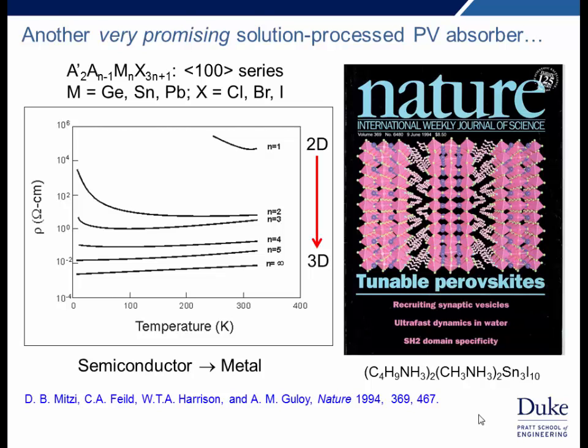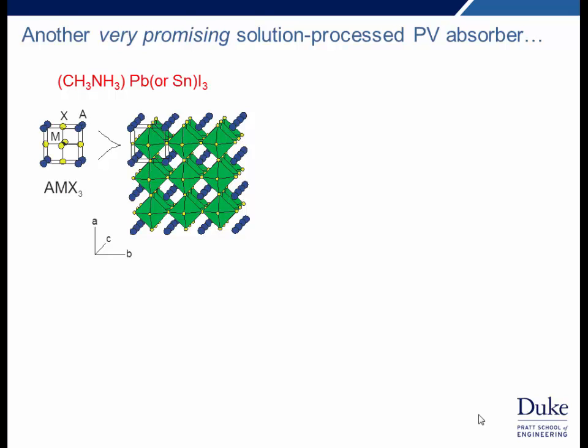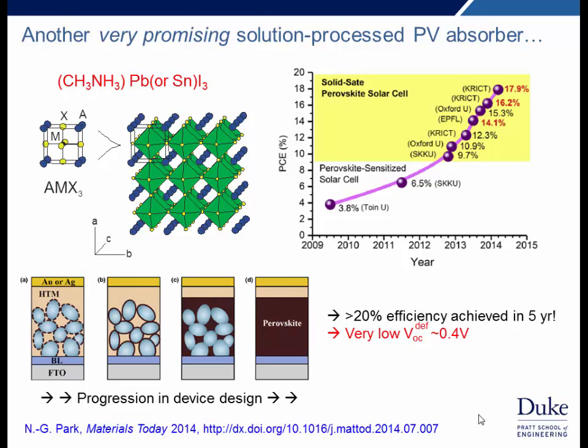If we use germanium, tin, or lead, we have this unusual case where we can get semiconducting metal halides, and as the dimensionality of the perovskite framework is increased by increasing N, we go toward progressively more conducting and even metallic character in these films. And this is exciting because it means we have a highly tunable, also solution processable at near ambient temperature semiconductor. The n equal to infinity compound that I'm referring to here is just the cubic or three-dimensional methylammonium lead or tin iodide material, which is the one that has generated a substantial amount of excitement because of the very rapid rise in efficiency that's been possible in this field of photovoltaics.